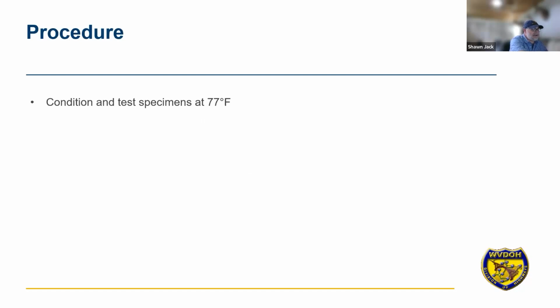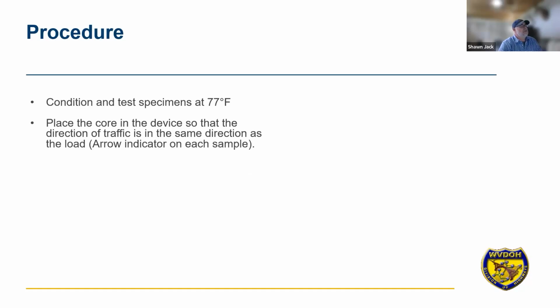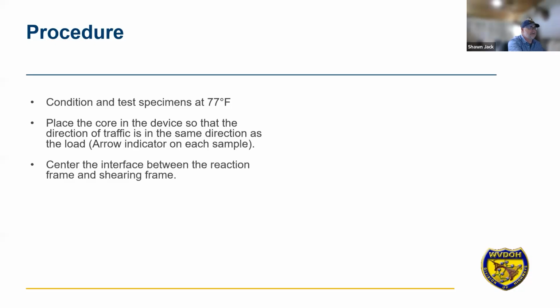So as a part of this procedure, we condition the test specimens at 77 degrees Fahrenheit. This is generally achieved for us in our specific gravity baths that we have readily available and already set to 77 degrees. We place the core in the device so that the direction of traffic is in the same direction as the load. And generally, there's an arrow indicator on each sample. Once in a while, we'll get one without one and we'll scream. But part of the process is we need to know the direction of traffic, and we tell all of our field folks to please put an arrow indicator on each sample. We're going to center that interface between the overlay and the existing layer, between the reaction frame and the shearing frame of our bond strength device, which I'll show you here in a few slides.